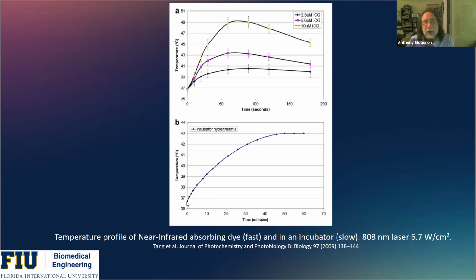If we place the same volume of solution in a cell culture incubator at 43 degrees, it takes about 1 hour to reach the 43 degree mark, whereas with the laser-induced hyperthermia, it occurs in about 1 minute, 60 seconds. So this time is seconds, this time is minutes. So 60 seconds to increase the environment to 43 degrees versus 1 hour to increase the environment to 43 degrees. So again, this is my model for a fast, localized hyperthermia, and this is my model for a more global, slower rate hyperthermia.